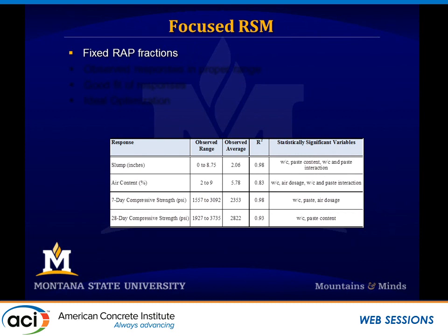We fixed the RAP fractions at 100% coarse replacement and 50% fine replacement, because one of our goals from the beginning was maximize the amount of RAP that we use in our concrete. We were getting a yield ratio of around 2 to 1. If I mentioned before, about twice as much coarse as fine. And so using 100% coarse and 50% fine yielded about that 2 to 1 ratio, so we could maximize the amount of RAP. And we knew that we could meet the minimum specifications with throwing all of the RAP into it. Okay. And so we fixed those things, and then we went on and looked for the paste content and the water cement ratio and the air dosage rate that met those specifications.